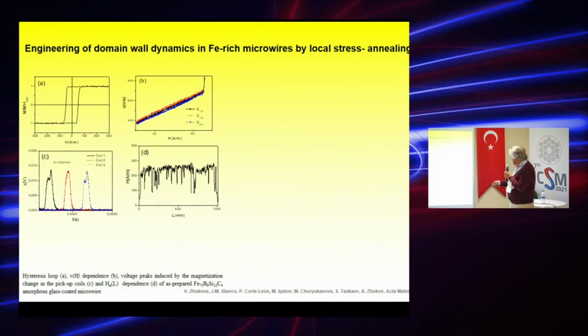Conventional ways, for sputtering for example, involve changing the composition during the process. In this case, we applied a method where we varied the temperature in the area where we place our materials subjected to stress annealing. So this is the length, and the temperature was varied, so it's a kind of temperature gradient. Once we stress anneal the sample under these conditions, we have different local hysteresis slopes in different regions of the microwires. Here is the length of the microwires, and the hysteresis slope measured at different temperatures.